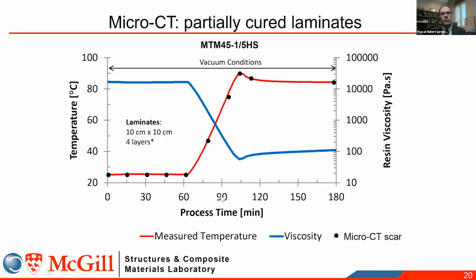So I'm going to show you some CT scans of a composite prepreg, an autoclave prepreg, and I'm going to take it through a typical cure. Here we see the temperature in red, rising to the cure temperature. And in blue, you see the viscosity of the resin decreasing to the minimum viscosity that will allow the resin to flow. And we're going to look at micro-CT images at different stages, as illustrated by this dot, where we stop the process and look at the material.